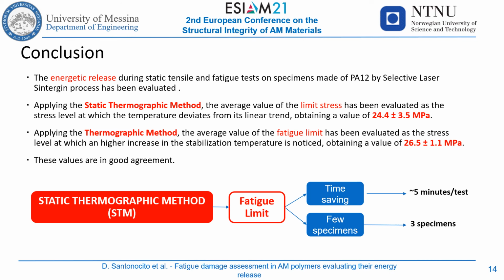By the thermographic method, the fatigue limit has been evaluated as the first stress level for which higher stabilization temperatures are observed. Its value is equal to 26.5 MPa. The limit stress is in good agreement with the fatigue limit, and it is a more conservative fatigue design parameter. For additive manufactured materials, given the strong dependence of the mechanical performance on the process parameters, it is necessary to evaluate the fatigue properties in a very short amount of time and with low material consumption. Hence, the static thermographic method and the thermographic method can be a useful aid.